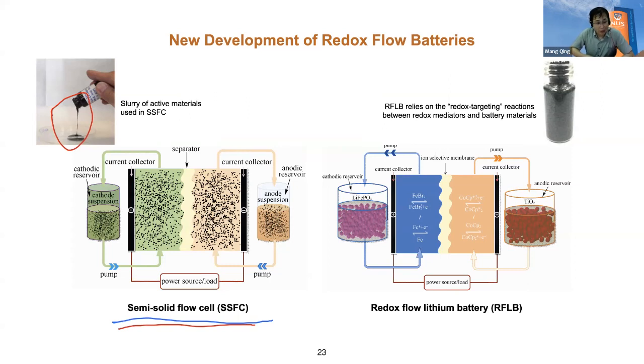But later they found, to make it work effectively, you need to add a lot of conducting additives, because if the particles are not connected, the charge needs to percolate from one particle to another. There's a lot of resistance. You need to add a lot of carbon additives, so they can form a continuous percolation network to make it work. And with these carbon additives, of course, the capacity is reduced and the viscosity also becomes high. And then the flow becomes more difficult. But it's still an interesting approach.